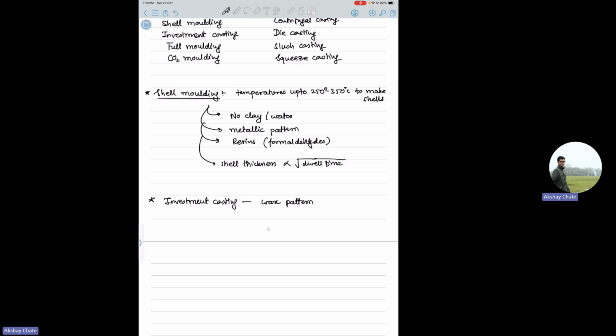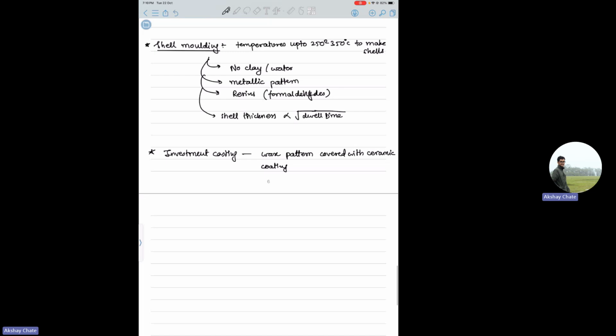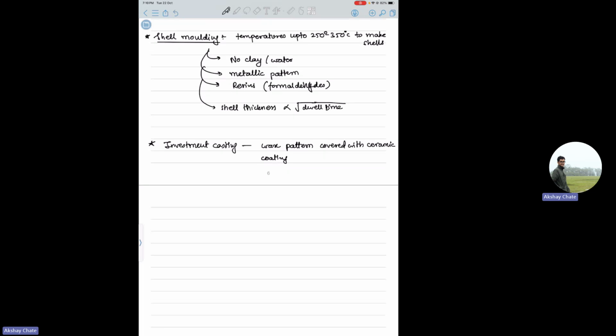Okay, so it's like shell molding, but it is done for higher temperatures. You can go to very high temperatures in this kind of casting. The strength will be more because you are using a ceramic coating. So the pattern is covered with ceramic coating, and then the wax is removed. Investment casting is used for high temperature applications or castings, such as gas turbine blades. You can see how high the temperatures have to go. Sometimes you can make dentures also using this, and medical implants, etc.